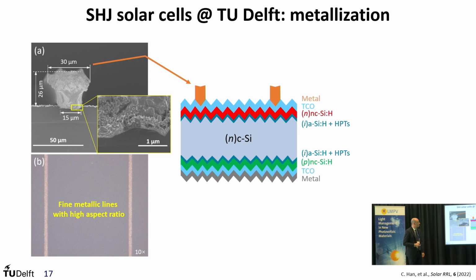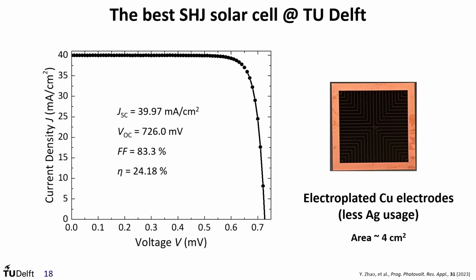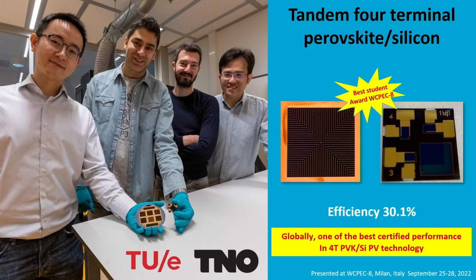So putting everything together, we could get one of our best silicon heterojunction solar cells in the range of 24% with an area of 4 square centimeters. And this type of architecture was essentially the basis, together with TNO and the University of Eindhoven, for what Albert mentioned before, to have one of the earliest demonstrations of 4-terminal devices where perovskite and crystalline silicon heterojunction were combined together.